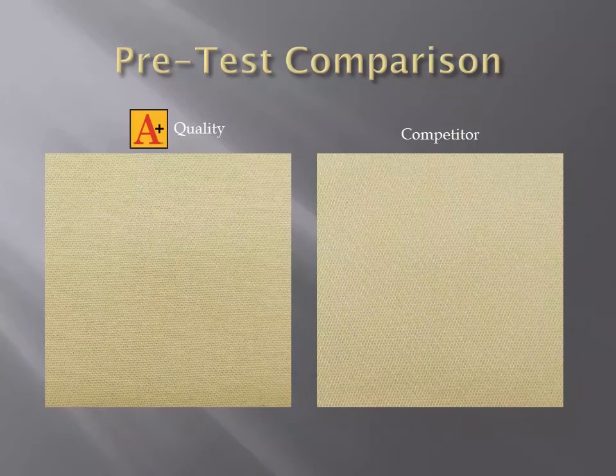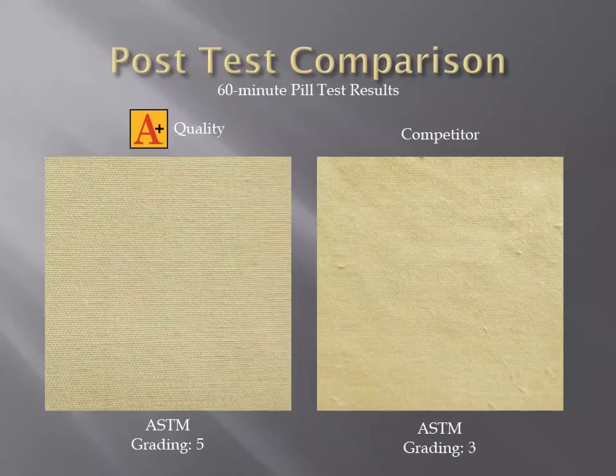Here we have 2 specimens of khaki stretch twill fabric for another example. Our mechanical stretch twill versus one of our competitors. This is before a 60-minute pill test. Again, they appear to be similar before testing. This is after a 60-minute pill test. The A+ specimen, once again, holds up much better under strenuous testing than the competitor specimen.